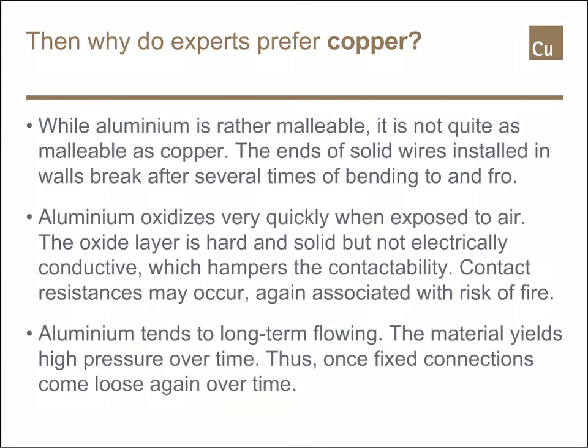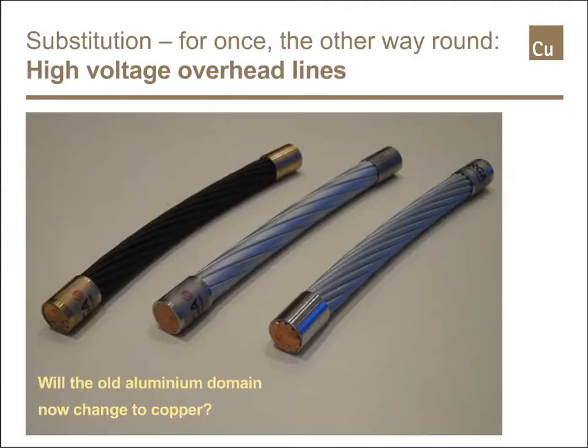And the third point is that aluminium tends to long-term flowing. That means the material is fairly soft, and under high pressure, it yields. It tends to yield, and contacts once fixed become loose over time and have to be re-screwed once a year or so, and that is not practical. Now, under the present price situation on the copper market, of course, we observe some substitution of copper with aluminium, but sometimes it also goes the other way around.